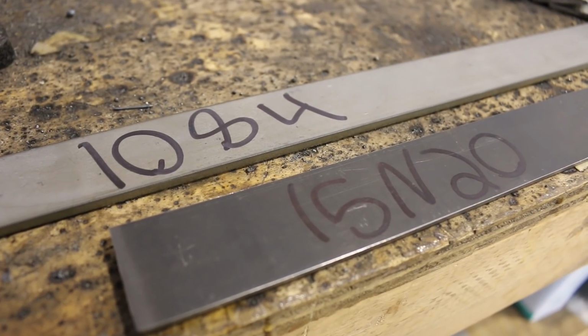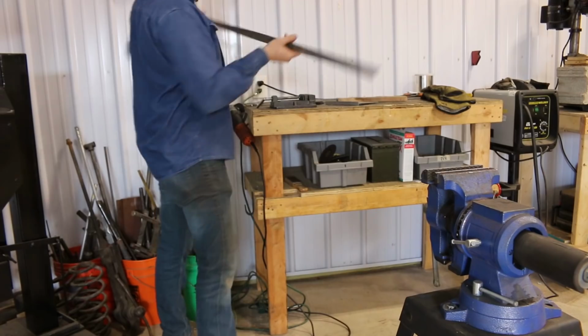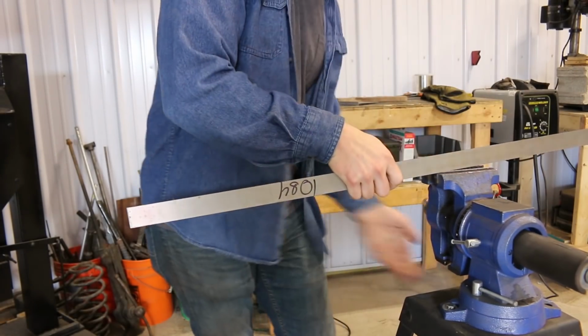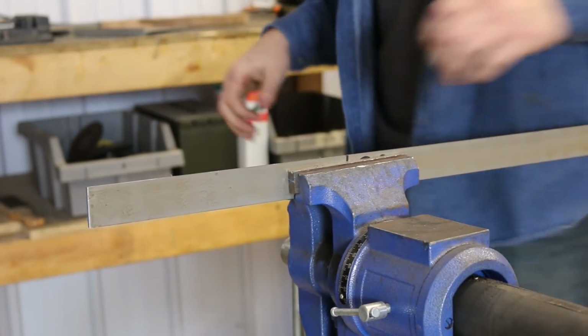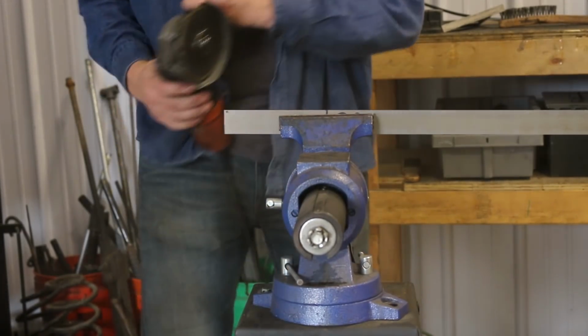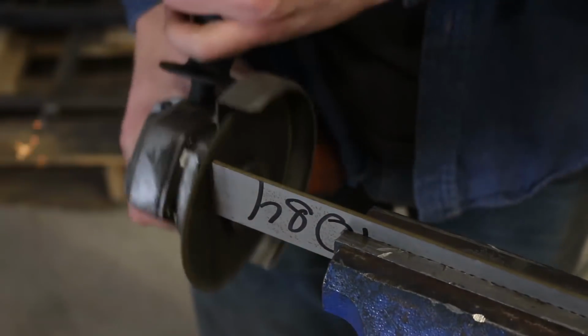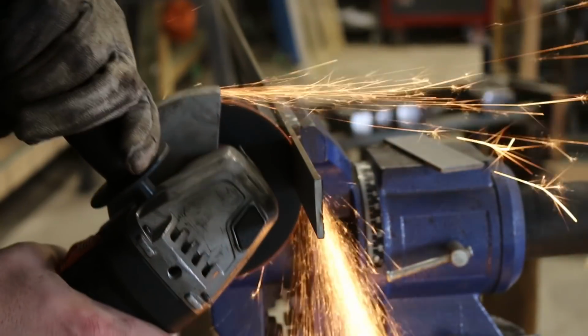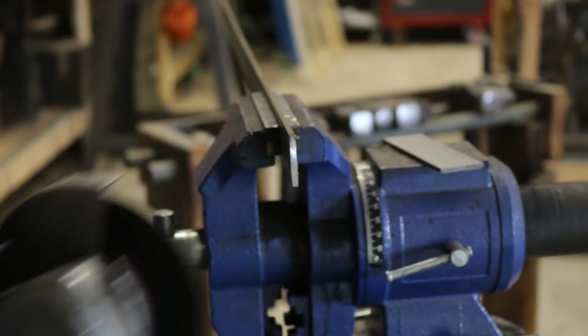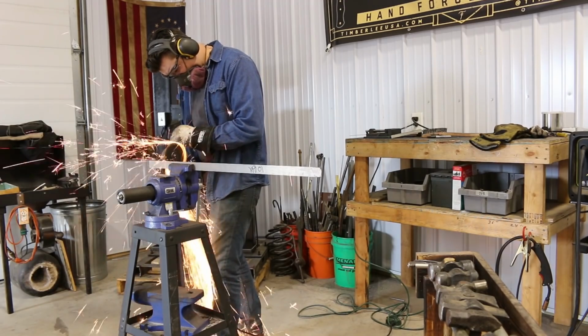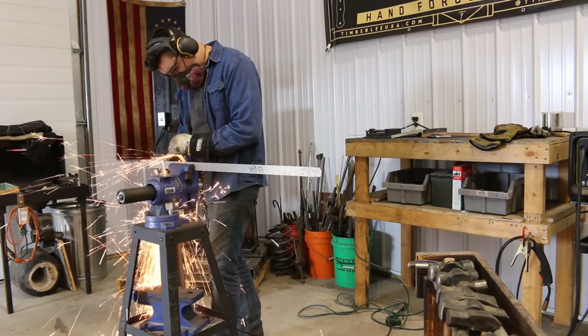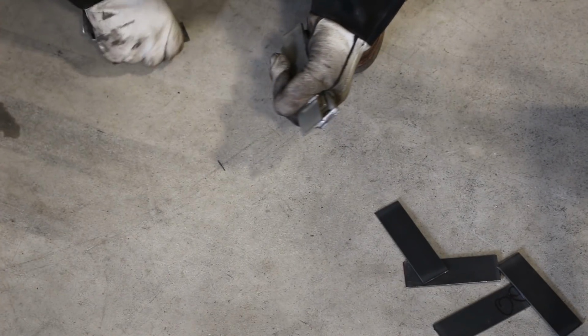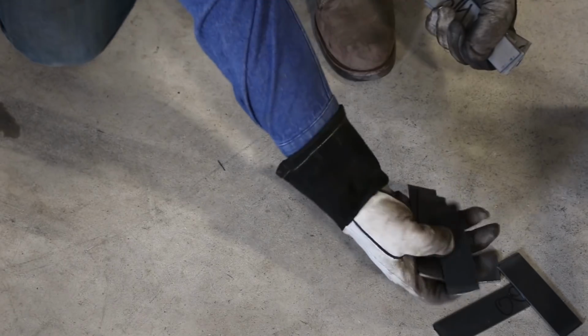All right, so for this billet, I'm gonna be using a mixture of 15N20 and 1084. Now, 15N20 has a 2% nickel content. And this is important to have in Damascus steel because the nickel is going to etch a lot differently than the other steels in the billet. And when you look at a finished piece of Damascus or a knife that's been etched, you'll see different colors, different streaks, and the shinier parts are because of nickel.